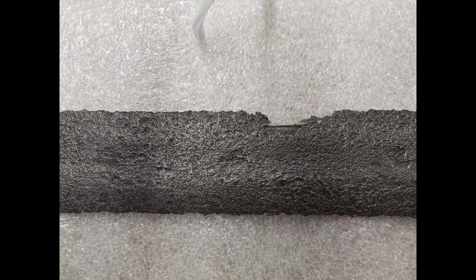The ratio of chemical elements that can be found in this sword is of course interesting to see if we can match those to a particular mine or ore deposit from a specific region and see if a match in local trace elements can be found. Especially since the chemical composition of the steel shows quite specific markers that can perhaps be tied to a local ore or mine. In particular, the sword shows quite a high cobalt concentration, but also furthermore contains copper, zinc, molybdenum of 0.07%, nickel, manganese, arsenic, titanium, chromium, vanadium, a little bit of lead and a very small amount of barium.